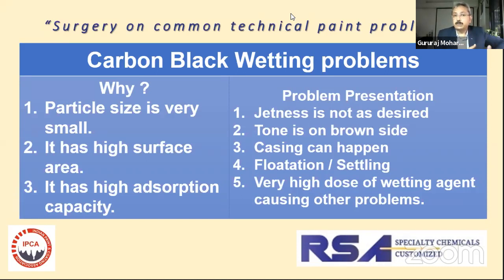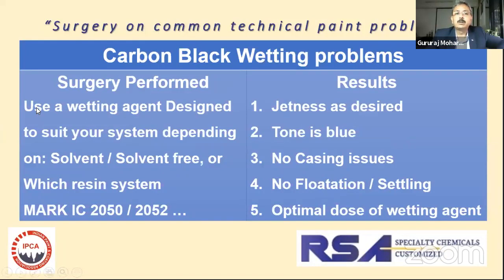And if you are not using a special product, the dose of the wetting agent will also be on a very higher side. So what's the treatment? Treatment is to use a specially designed wetting agent for carbon blacks. There are many again here. You'll have to select one based on whether your system is solvent based or solvent free, which resins you are using. So you have options. Go ahead and select options. Make an educated selection.